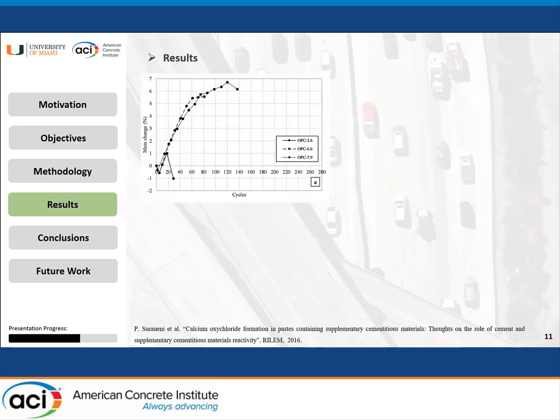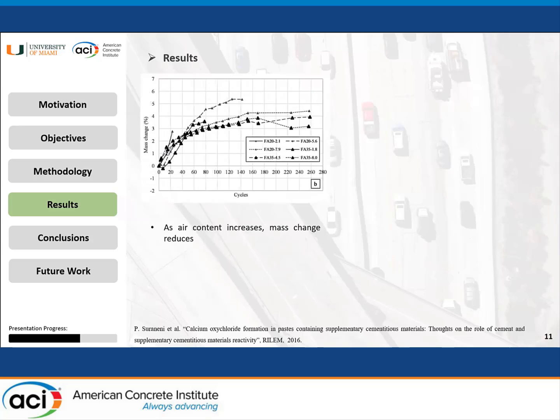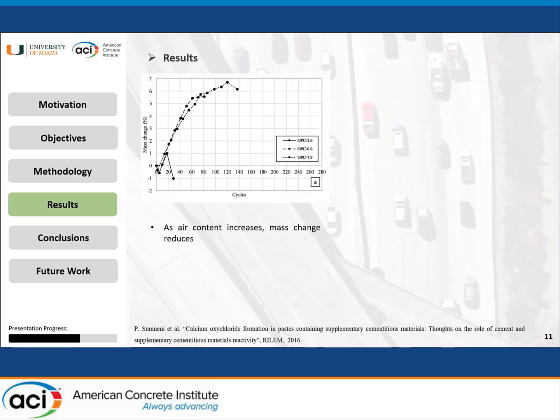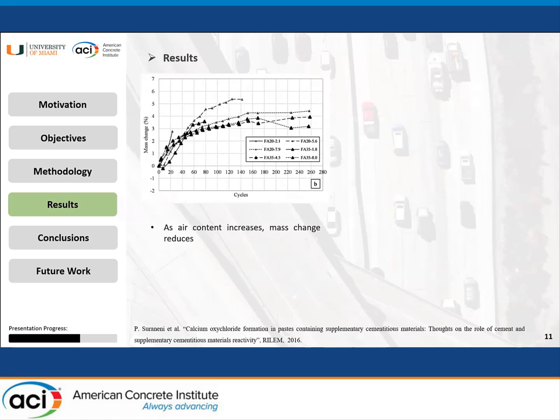All right, in here you see the mass changes which we kept measuring as the cycles were happening, versus the cycles on the horizontal axis. This is the figure for our control mixes having different amounts of air. So as the air content increases, the mass change is reduced. It's the same case for the samples containing SCM.